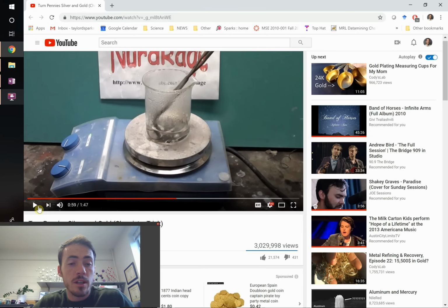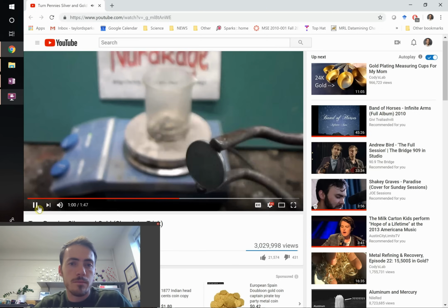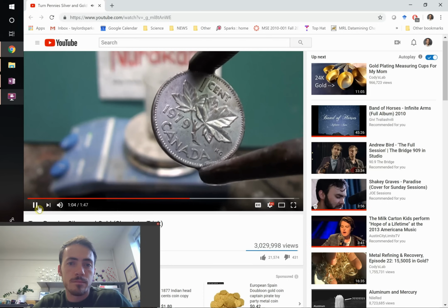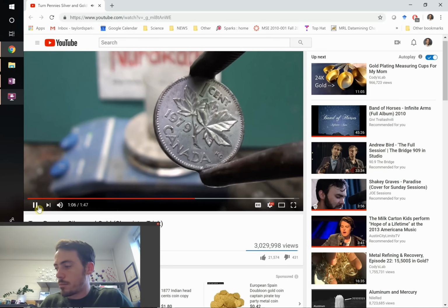We had zinc ions in solution. If you look up the standard reduction potentials, you would see that one of these is more favorably oxidized than the other. In fact, the one that's being oxidized is the zinc, right? So you're losing zinc, it's dissolving, and you've got these zinc ions in solution already, and they're going to be reduced onto the copper metal, right? So they're plating onto it, which makes it look shiny. Just turn a copper penny into a silver one. Sure, it's a trick, but it looks cool.